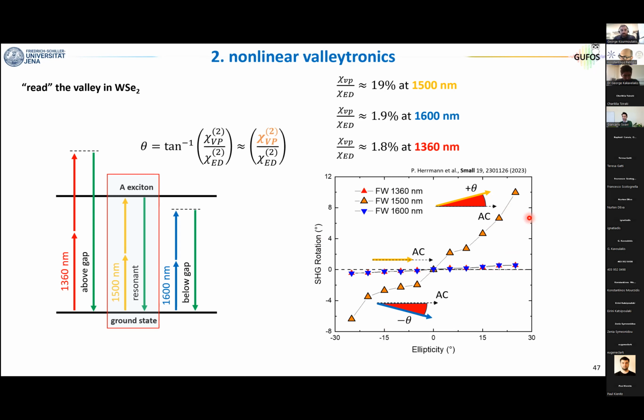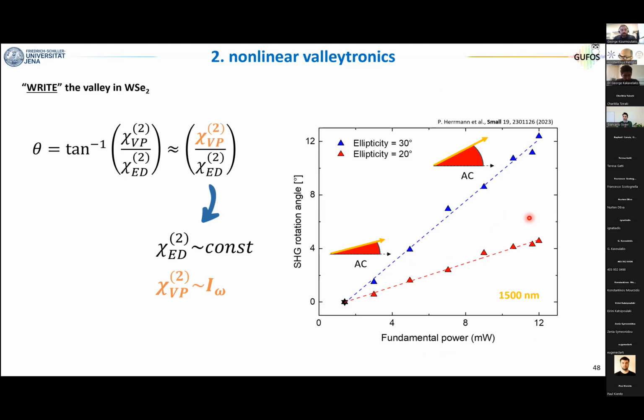Okay, so this is a very powerful method, and there is one additional element that I want to mention, and then in the last 5 minutes, I will try to tell why this is important. It's the fact that while the electric dipole response, so the nonlinearity coming from broken space inversion symmetry, is constant with power, an intrinsic property of the material, the one coming from broken time reversal symmetry is a function of the power. And this is because we break time reversal symmetry, so we generate the valley imbalance with the same pulse that we use to read the valley imbalance.